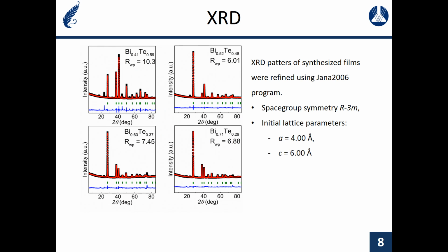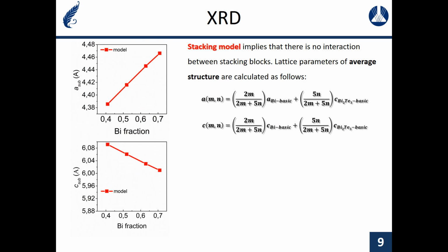X-ray diffraction patterns correspond to high degree of crystallinity of the synthesized bismuth tellurium films and show no peaks related to other phases. The position of peaks is slightly variable. We applied profile fitting to determine the corresponding variability of the lattice constants. What we expected to find out from the refinement? In literature, the compounds of this series are described with the so-called stacking model. The stacking model assumes no interaction between stacking blocks. Lattice constants, according to the stacking model, can be calculated using the following formulas.